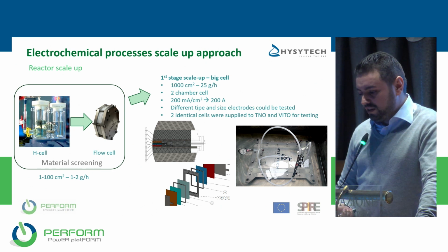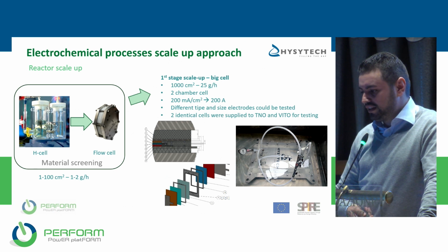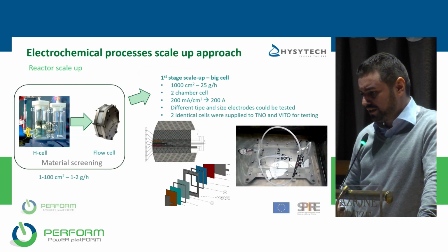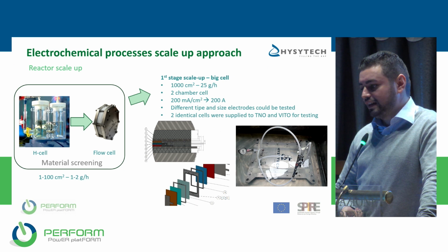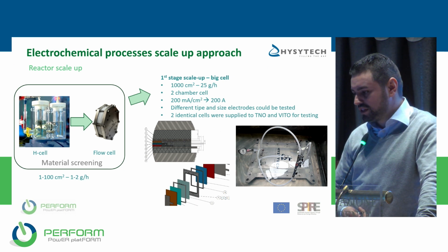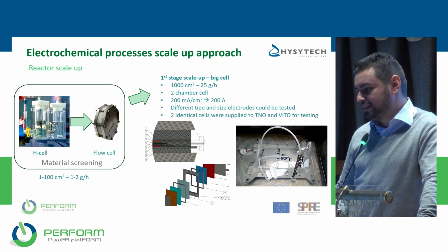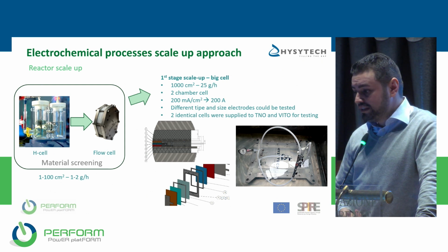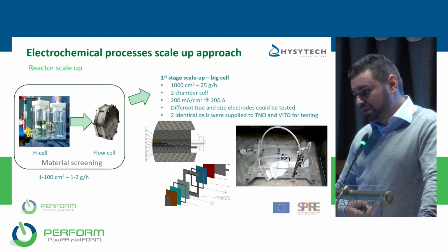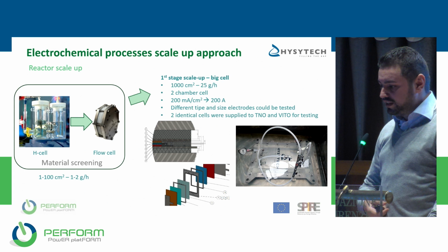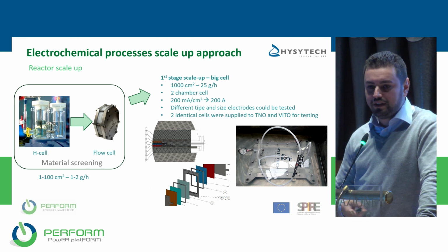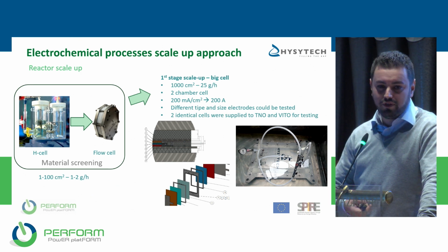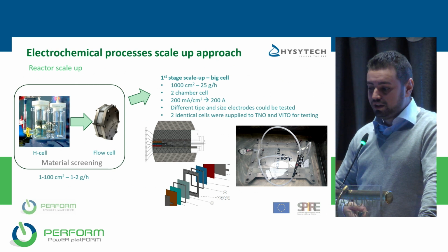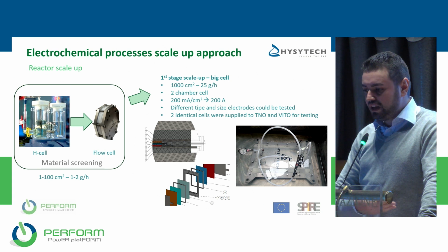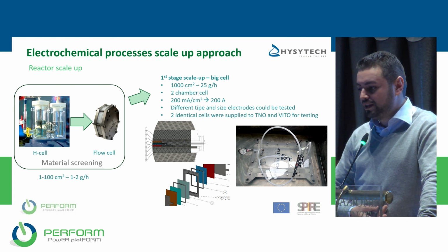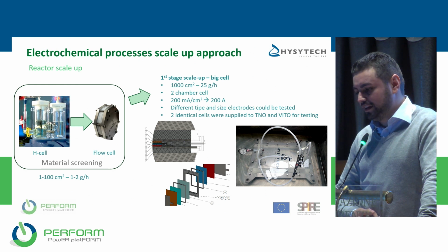If we take a closer look at this scale up, in the single cell, we had, as mentioned, a 1,000 square centimeter cell that has 2 chambers. The specification was to reach up to 200 milliamps per square centimeter in terms of current density. This means that the cell should bear at least 200 amps. We had to design the cell in such a way that we can use different types and sizes of electrodes, in order for the partners to develop them and to understand which is better for which application that we were testing. And we supplied to the 2 lines that were being developed, TNO and Vito, 2 identical cells to start testing the chemistry in them.